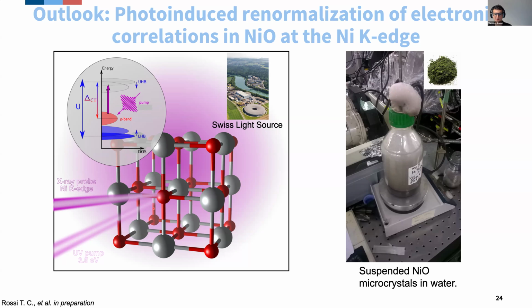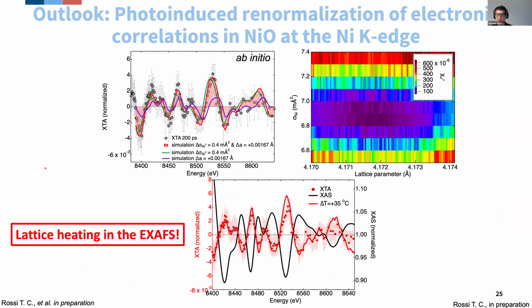And we excite the nickel oxide with a pump of 3.5 electron volts, and we probe the system at the nickel K edge. And the results we got should not be surprising to you: with the 200 picosecond time resolution that we had during this experiment, what we observed in the EXAFS is a lot of lattice heating again. But this time, because the crystals were not thin films, but actually particles, we were able to quantify by how much the Debye-Waller factor and how much the lattice parameter changes in the excited state.